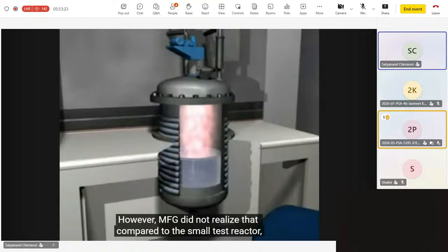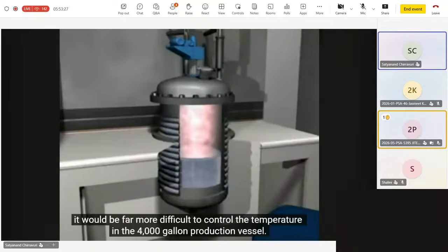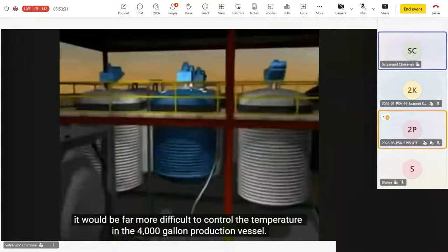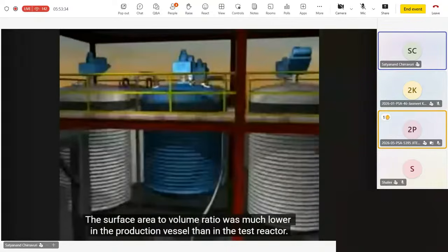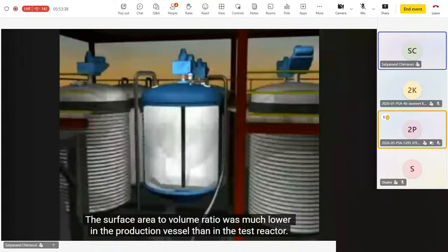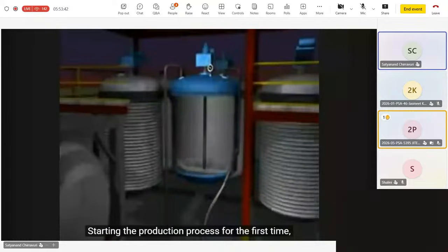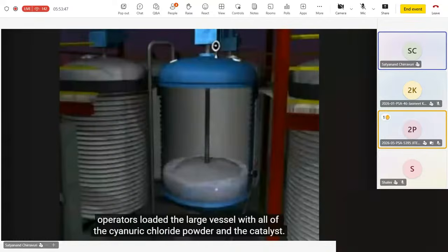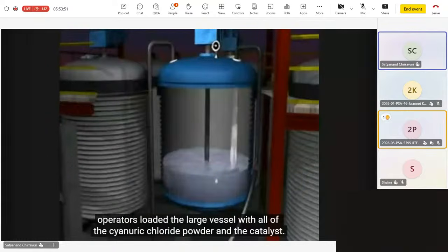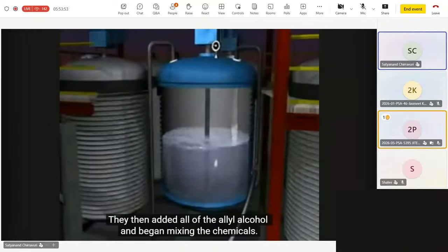However, MFG did not realize that compared to the small test reactor, it would be far more difficult to control the temperature in the 4,000-gallon production vessel. The surface area to volume ratio was much lower in the production vessel than in the test reactor. Starting the production process for the first time, operators loaded the large vessel with all of the cyanuric chloride powder and the catalyst. They then added all of the allyl alcohol and began mixing the chemicals.